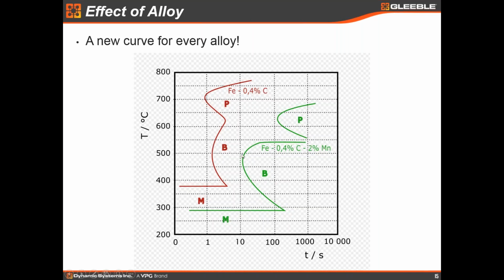So we would say this steel has a better hardenability because I can quench in martensite much easier in this steel. So it's a more hardenable steel. And manganese is, of course, a well-known hardenability element. Chromium, molybdenum, boron, or other hardenability elements can delay some of these transformations and allow this steel to be more easily hardened with a lower quench rate. And of course, if I have a lower quench rate, I can avoid some quench cracking and some other problems.